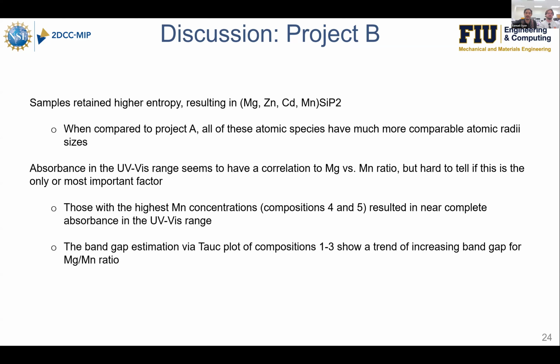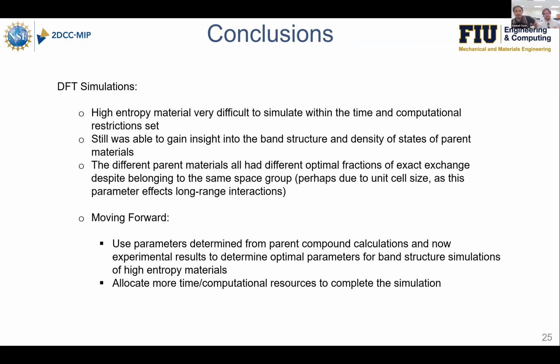There was some trending data that we were able to get, specifically with magnesium and manganese. However, the relation is pretty weak with an R value of about 0.6. So probably a lot more synthesis and crystal growth will have to be done to validate whether this is a legitimate trend that can be established or not, but at least it's good preliminary data for the crystals that were synthesized.